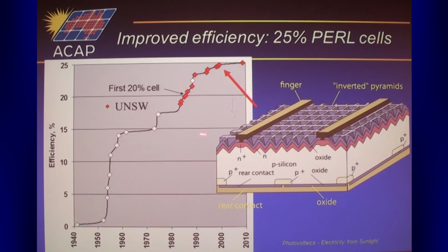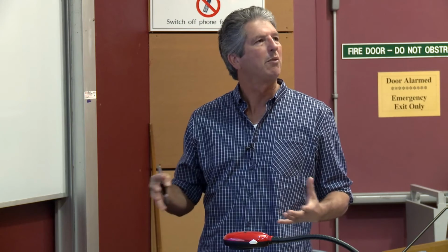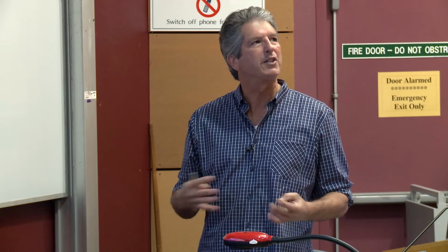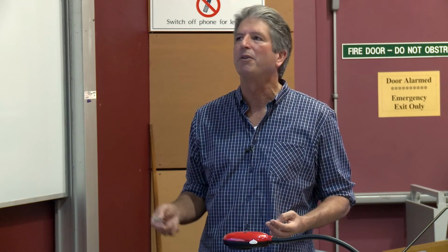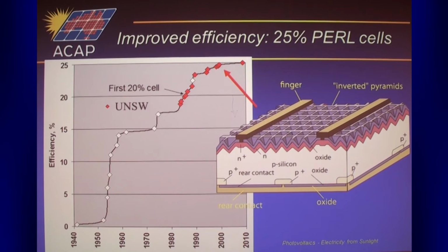So we used all the tricks that we found for, that we used in our 20% efficient cell. We've gone to a more sophisticated texturing approach, sort of a 3D approach. And this one was chosen and designed to maximize the light trapping in the device. So we incorporate features into the exact patterning and so on that enhance the amount of light that gets trapped in, and we get quite close to that 50 times trapping of the light within the material.